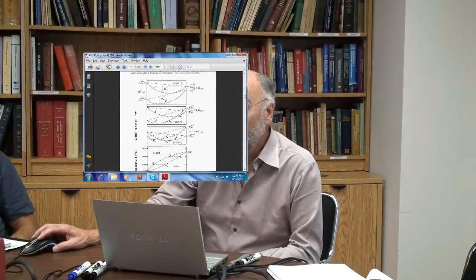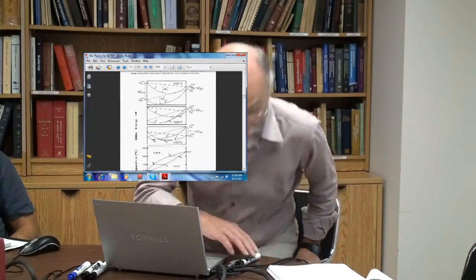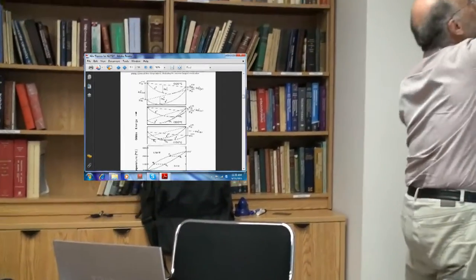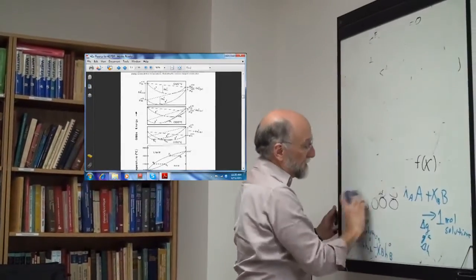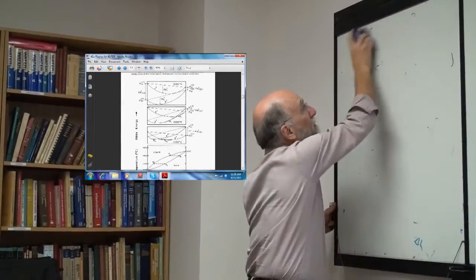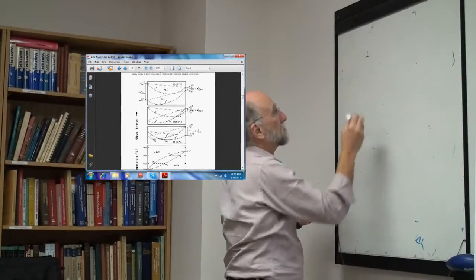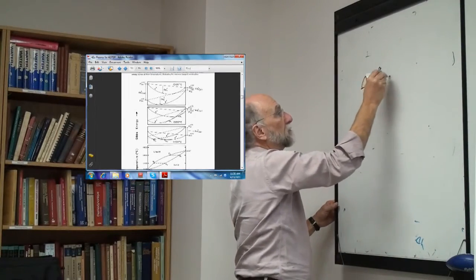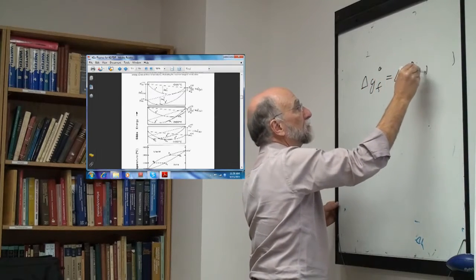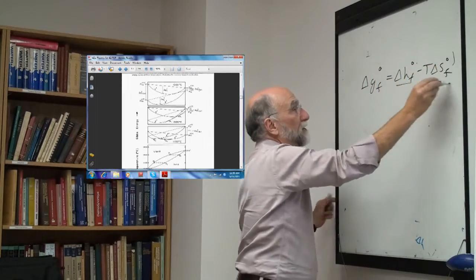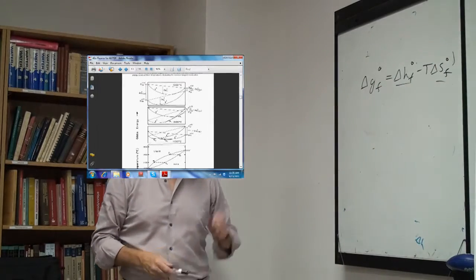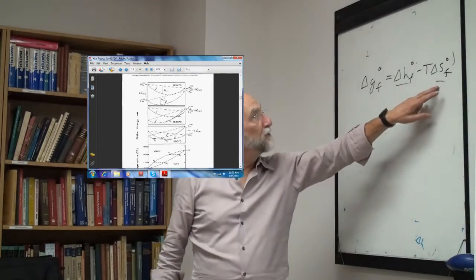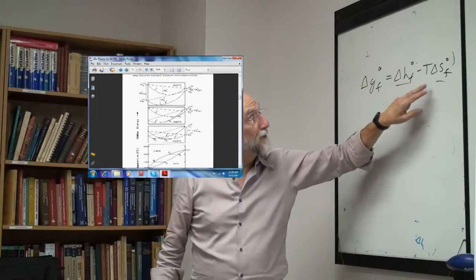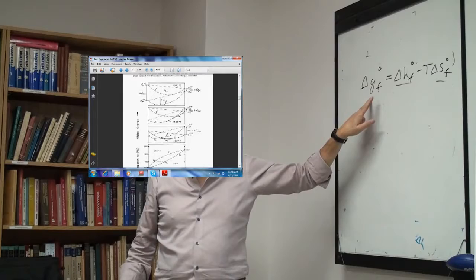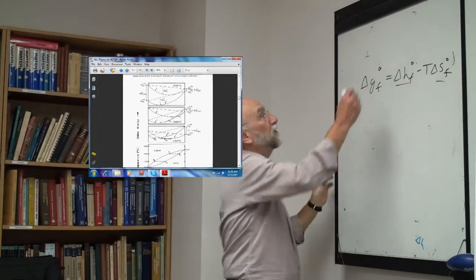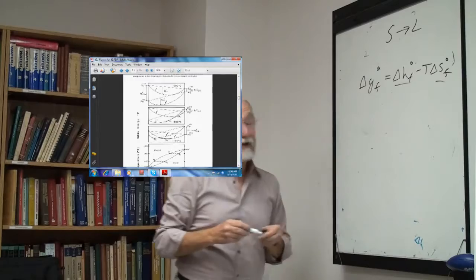So what really happens is, as you lower the temperature, the Gibbs energy of fusion is equal to the heat of fusion minus T times the entropy of fusion. The heat and the entropy of fusion are both positive. If you're at a high temperature, the entropy of fusion term predominates, and delta G of fusion is negative. That's delta G of fusion going from solid to liquid, so the liquid is more stable.